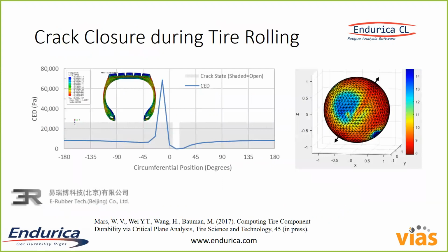Here's an example of that for a tire model. This is a straight ahead rolling under a load, and the blue line represents, think of this as the energy release rate on the crack as it goes through one revolution of the tire. The center of the footprint of the tire is 0 degrees. You can see when we're at the top of the tire, far away from the footprint, there's a small amount of load. That's probably due to the inflation pressure of the tire.